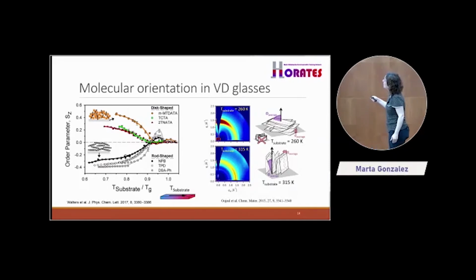Okay, if we are at equilibrium, this parameter Sz tells us the order. Let's say that if the molecules are more or less parallel or perpendicular to the substrate, a 0 means completely disorder, completely random. Okay, if we start going down in temperature, we see that the molecules tend to align. Okay, it's not that they are like this. Tend to align perpendicular to the substrate, okay? And if we go to lower temperatures, the molecules tend to remain flat. Still disordered, but flat.